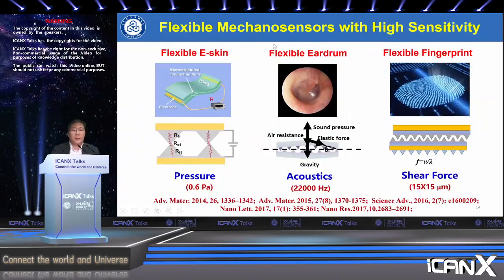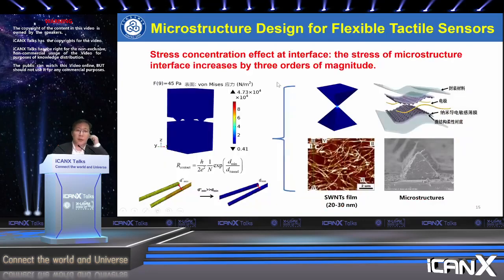Based on this principle, we developed a series of flexible mechanical sensors with high sensitivities. For example, for flexible electronic skins, we get a very low detection limit of about 0.6 Pa. For acoustic signal detection, we call it the flexible bionic eardrum, and we get a wide range of detection frequencies. And for shear force detection, we call it the flexible fingerprint, and we can accurately detect the texture of a surface. So in the following slides, I will describe our progress in these directions.